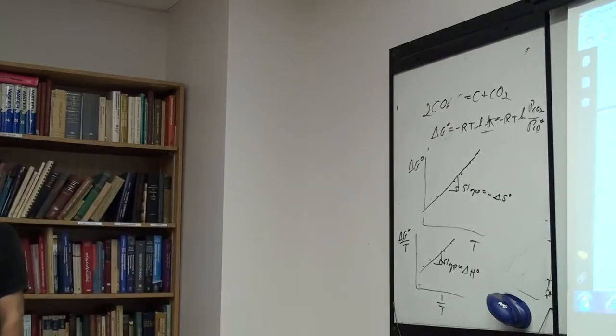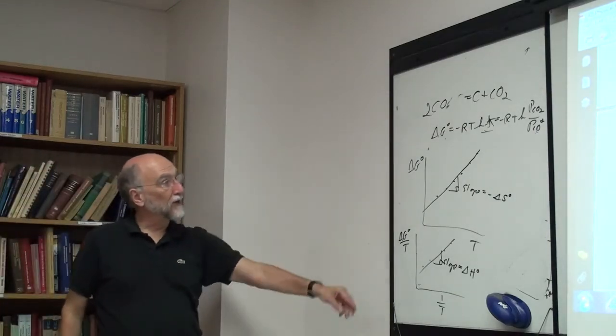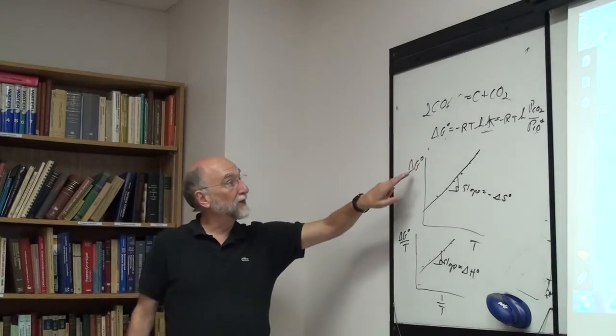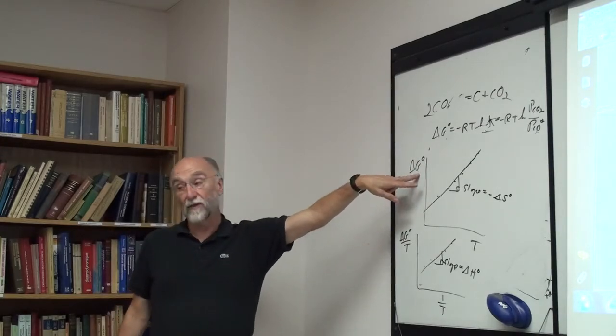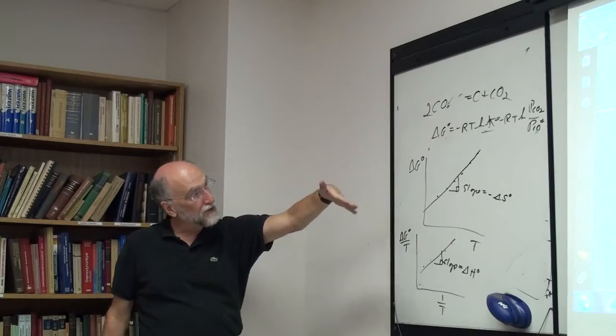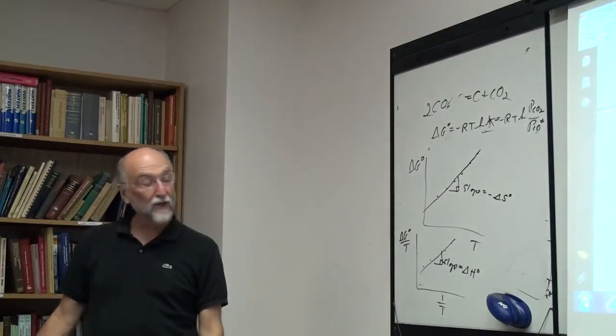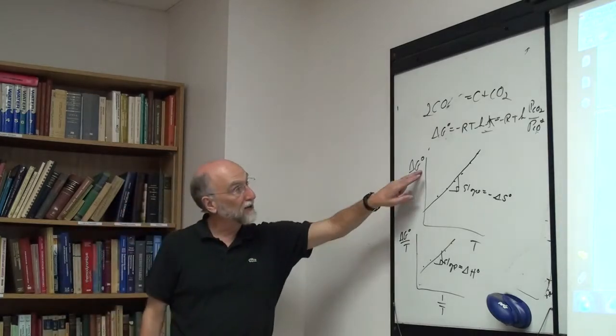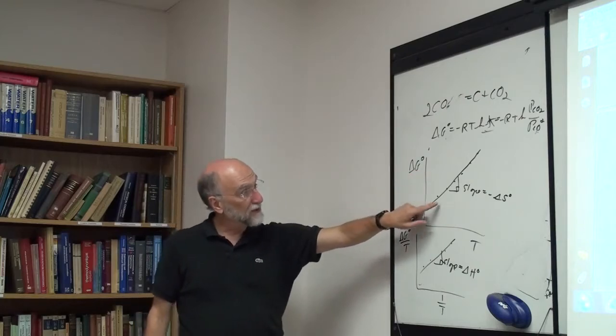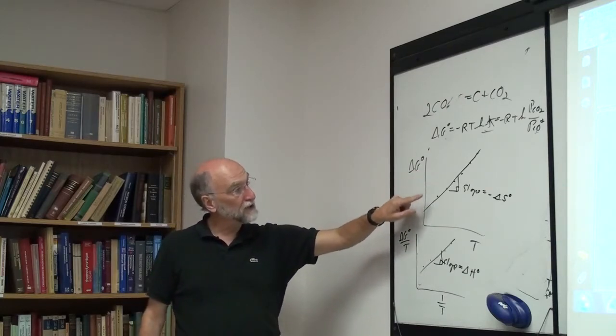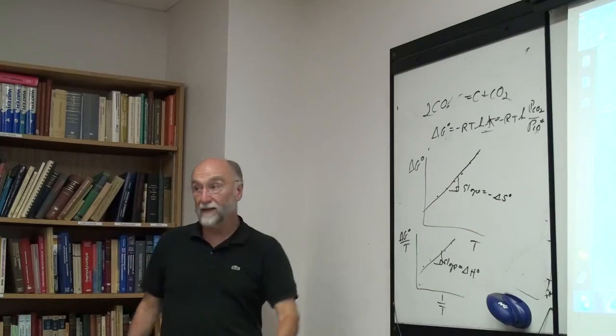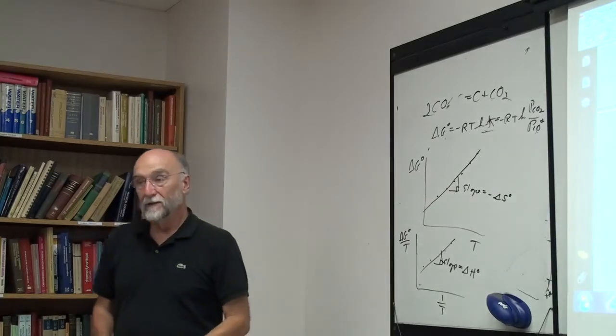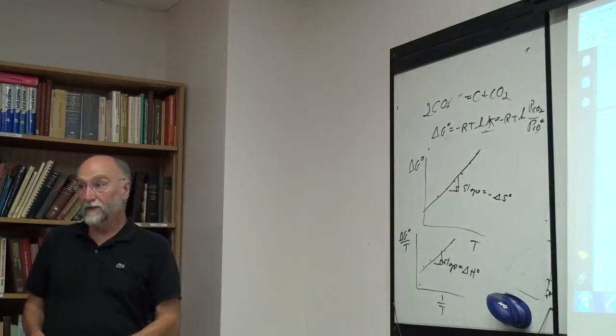Okay, so I measure by setting up an equilibrium, and this could be measured by the gas equilibrium, or the delta G measured from the electrochemical cell. My cell I just showed you, zinc plus chlorine forms zinc chloride. I could set up the electrochemical cell and measure the voltage, giving me at a given temperature the delta G. I do that at several temperatures, draw the line, I can get the entropy of the reaction. Okay, or the heat of the reaction if I do it that way.